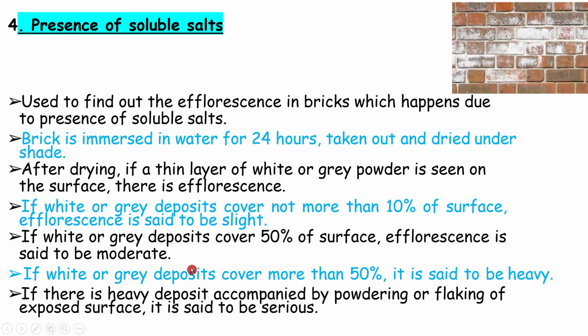If white or grey deposits cover not more than 10% of the surface area, efflorescence is said to be slight. If it covers up to 50 percent, efflorescence is moderate, and if it is more than 50 percent, it is very heavy and we have to take care. If there is heavy deposit accompanied by powdering or flaking of the exposed surface, it is very serious.